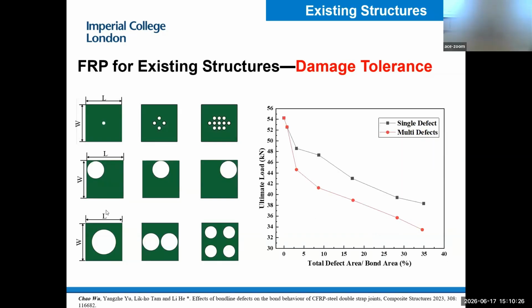It's very interesting. The vertical axis is the interface loading capacity, and the horizontal axis is the size of the defect in the bond line. It's very simple: the larger the defect, the smaller the capacity of the bond line. You don't have to do any test to know that. But the interesting result is if you look at these two curves.